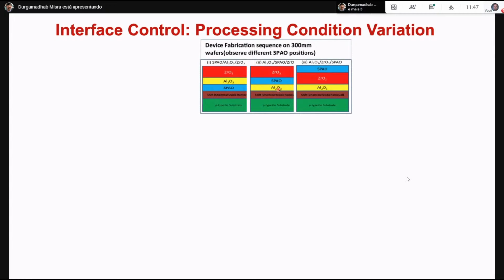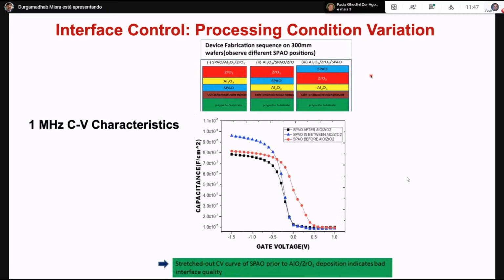Oxidation, and then after aluminum deposition, we also did the plasma oxidation, and then after aluminum oxide and zirconium oxide were deposited, we exposed it to the slot plane plasma antenna. So that showed much better. Once we have this in between, in this case, it actually improved the depletion capacitance, which means it improved the EOT values.